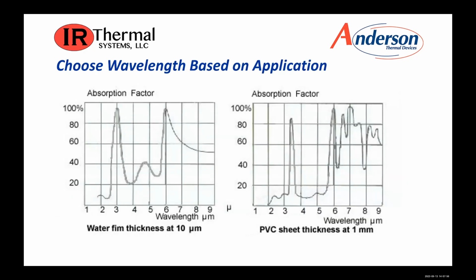So you choose the wavelength based upon the application. Here is a slide with two different materials. On the left is a water film thickness at 10 microns. You can see the absorption factor at 3 microns and 6 microns there. On the right, you have a PVC sheet thickness at 1 millimeter, and there you have a different set of wavelengths at roughly 3.4 micron, and then the others there on the right, where you would want to pick the lamp and the wavelength based upon that application.